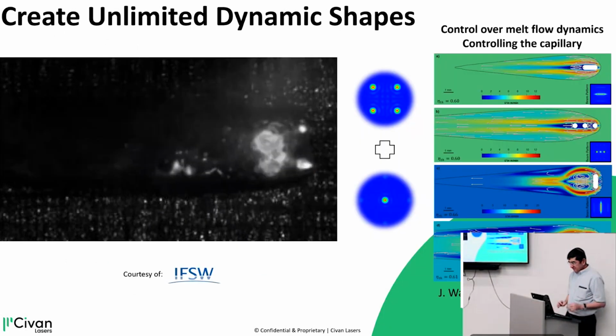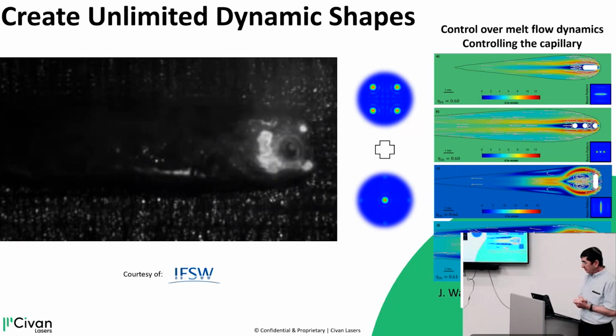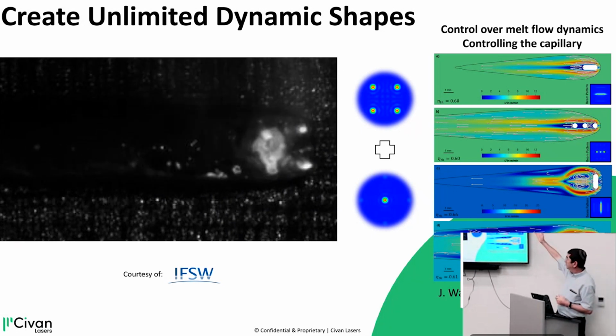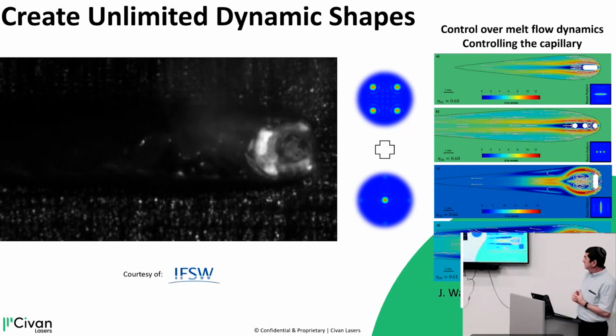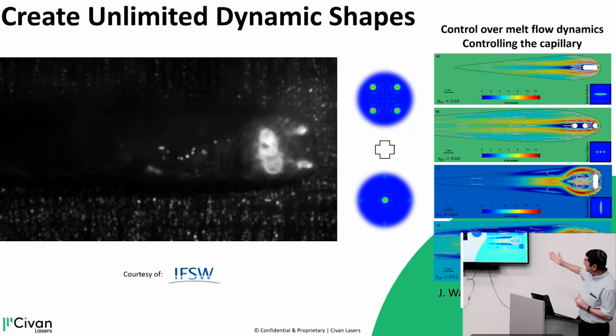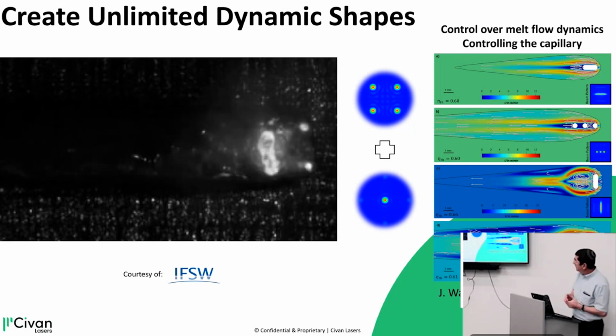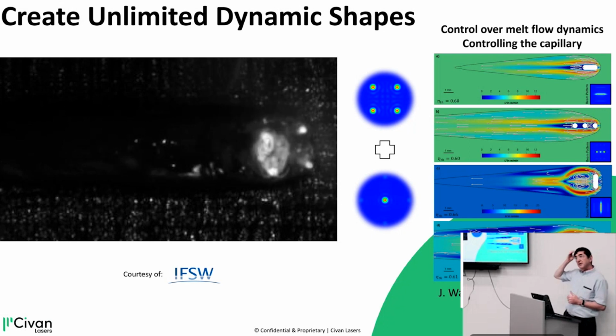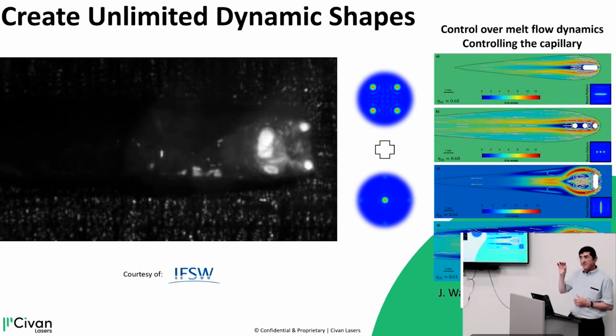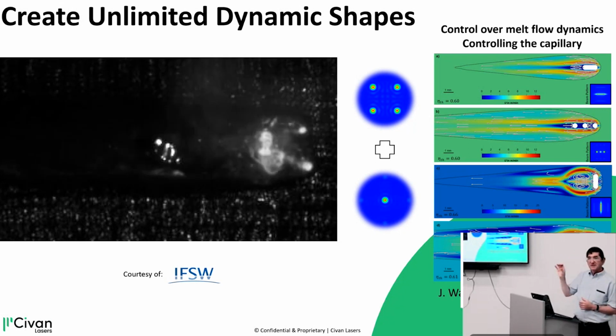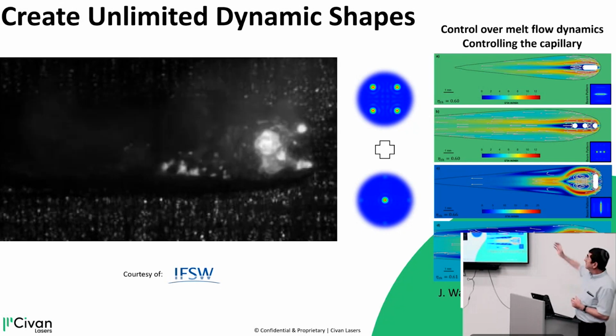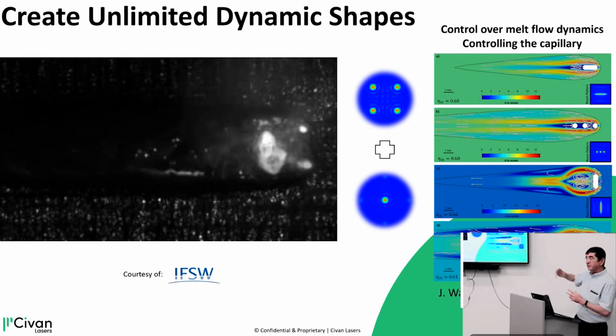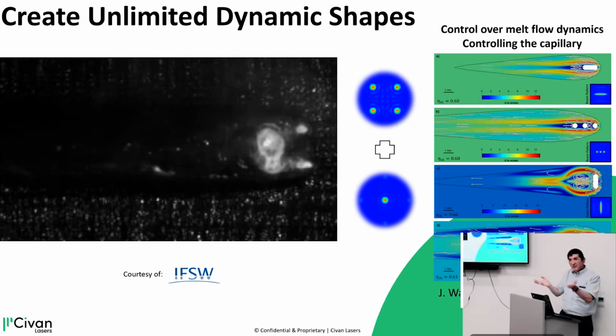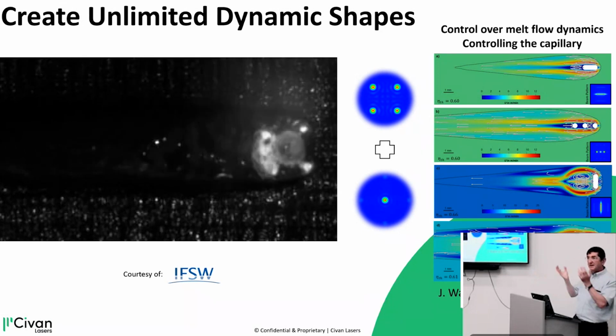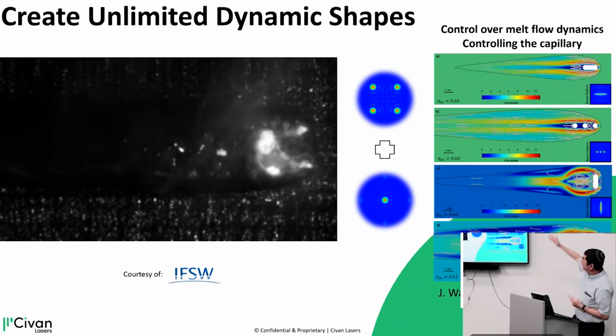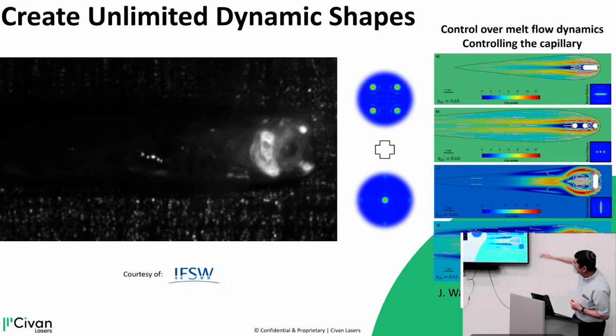Okay, so what do we do with it? So here's an example. On the right, what you see is simulations. This is from IFSW in Stuttgart. And the color code here is speed of molten material inside the melt pool. And you see that you can design different beam shapes to create different currents of the liquid metal inside the melt pool at different speeds and different geometries.